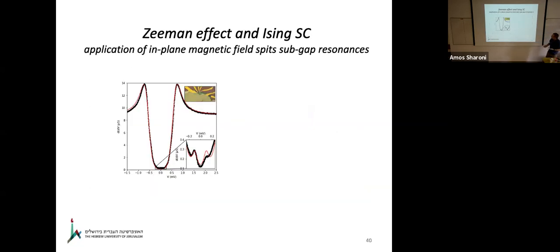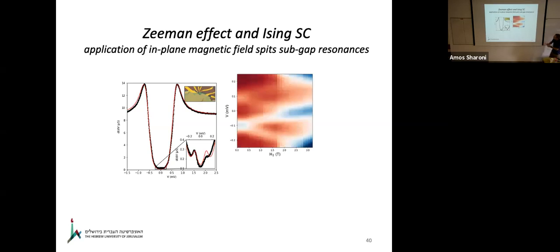Now, if you want to say something quantitative about these subgap states, we start applying an in-plane magnetic field. Luckily, since this gap is going to survive into a few Tesla, unlike non-layered superconductors, like the regular metallic superconductors, what you get are these two features, and you see them splitting versus in-plane field here up to 3 Tesla. They are at plus and minus 100 microvolts, and they meet somewhere around 2 Tesla. Now, how do we know that this is a defect?